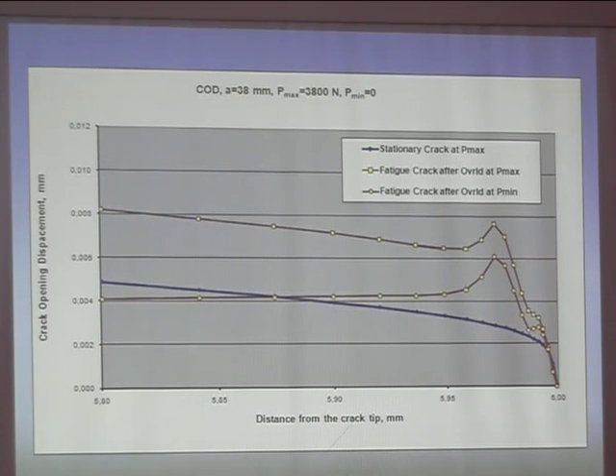So very often, I'm not sure whether what I'm saying is 100% sure, but I think that very often in the experimental measurements which we make, measuring the change of displacement, when there is no change of displacement, we say it's closure. But it doesn't necessarily need to be. It can be just that the plastic zone is becoming so hard that it doesn't deform anymore.